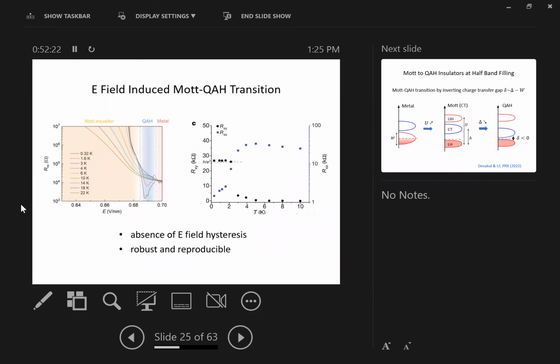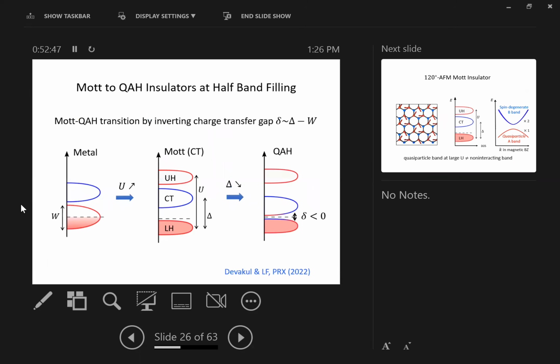Also, the experimental data shows that the transition from the Mott insulator into the quantum anomalous Hall state seems to be continuous. There's no electric field hysteresis. And the onset of the quantum anomalous Hall phenomena occurs at about 3 Kelvin. It's quite decent. Yeah, a quite decent quantum anomalous Hall system. The data has been reproduced in several devices. So this leads us to think about why a Mott insulator can continuously transition into a quantum anomalous Hall state. This summarizes the essence of our theoretical understanding.